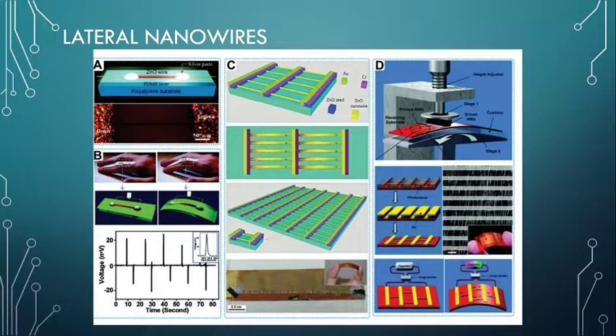For enhancing the output of zinc oxide-based PENGs, a direct approach was to integrate numerous lateral zinc oxide nanowires in a single device. As shown in Figure C, nearly 700 rows of zinc oxide nanowires were integrated on a single flexible substrate in a parallel configuration. Each row in this configuration contained about 20,000 zinc oxide nanowires. This made the whole device exhibit great flexibility. The lateral zinc oxide nanowire array was utilized in a sweeping printing method to fabricate a high output PENG, and this was reported by Zhu and his group.